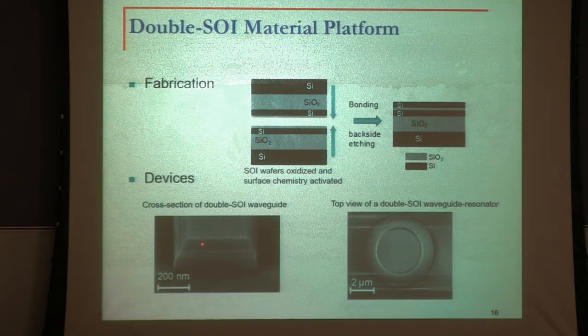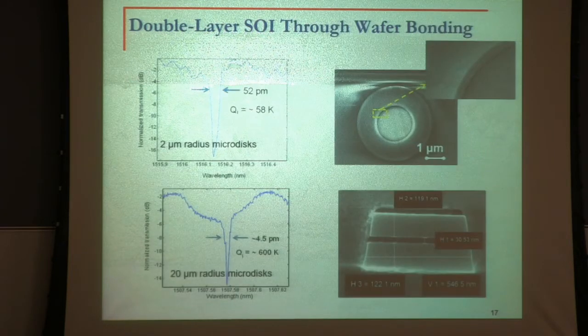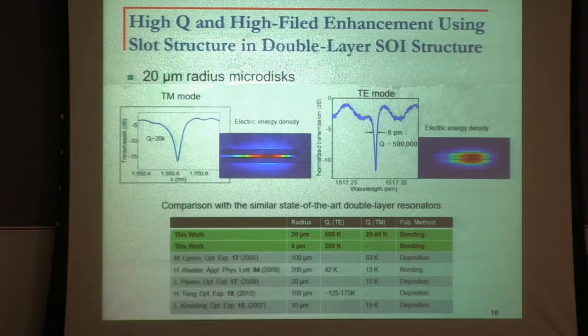But then this is what we get. This is a waveguide. Silicon, and the middle oxide is probably visible, even from a distance. And then the resonator. Now, using this material, we were able to demonstrate resonators with quality factors that are in the ballpark of the single-layer silicon. That means the quality of the material is not sacrificed, both for small resonators and large resonators. A comparison of this work with other works, the quality factor with size. Our case was bonding. There's deposition, bonding, deposition, and deposition. And you can just compare the numbers to see the quality is really improved.